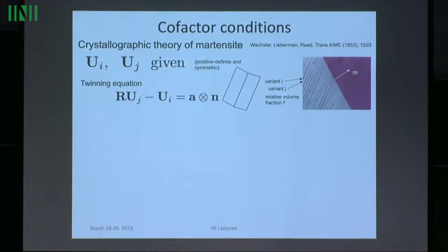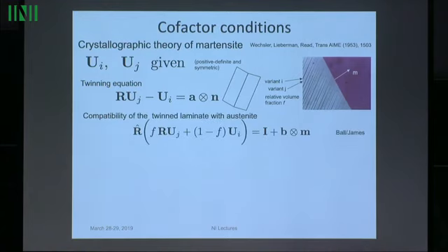So recall this microstructure. There it is. It was governed, let me remind you about the algebra that goes behind it. First of all, there's this so-called twinning equation that governs the compatibility of these interfaces. And then there's another equation which reduces the transition layer energy to 0, or to as small a value as you want, by making these bands finer and finer. And that's governed by this equation. So that's the algebra behind that.